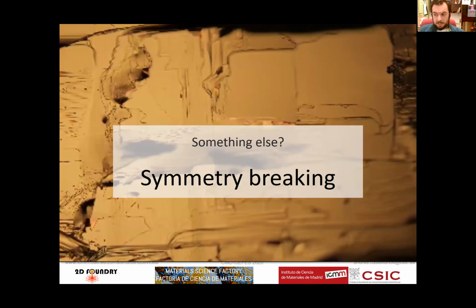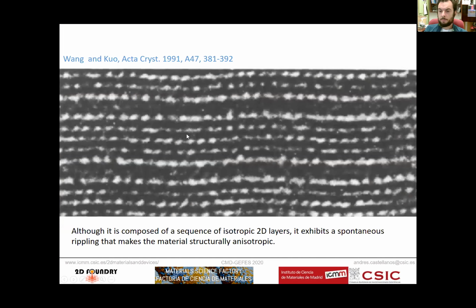So is there anything else this interaction between the layers can do? As I told you at the beginning, and I just told you already the highlight of the talk, this weak van der Waals interaction can also break the symmetry of the system. Already in the 90s, apart from the previous TEM measurements I showed you, other groups doing cross-sectional TEM were seeing that frankeite had these kinds of waves in the cross-section. This is kind of funny because the tetragonal and hexagonal layers should be isotropic in plane. But the superlattice has this anisotropy, these ripples.